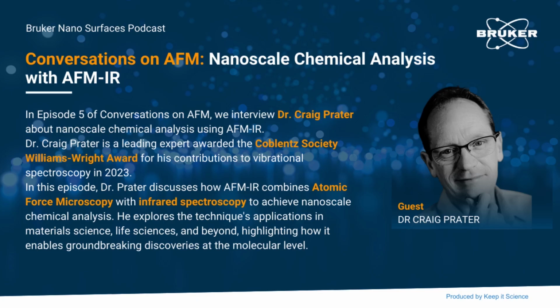Sure. So as you mentioned, AFM-IR is a combination of two well-established techniques, atomic force microscopy and infrared spectroscopy. And backing up a little bit, I want to talk a little bit about the motivation of AFM-IR, and then I'll talk about how it works. So for an extended period during the development and use of AFM, there was a very common challenge where AFM really excelled at achieving very high spatial resolution, making beautiful images of a wide variety of samples. But one of the most common questions is we would look at an AFM image of a sample and we would see some interesting structure. We would go, well, what is that? And the AFM was not very good at answering the question of what is that?